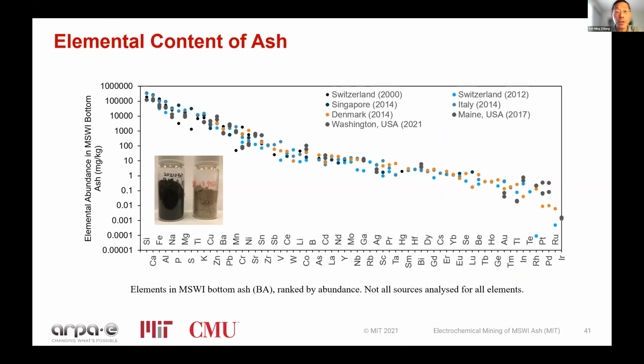So the inset image there, this is what this ash looks like. It can be black, it can have carbon in it, it can be sort of brown or somewhat gray. And so silica, there's more silica than anything else. And here's iron, right? But as you see this cascade come down, you see that the world over, if we blow this up to a linear scale, there are wide variations in the elemental content. But on a log scale, you see that these are the ashes for 7 different sources, 7 different analyses.